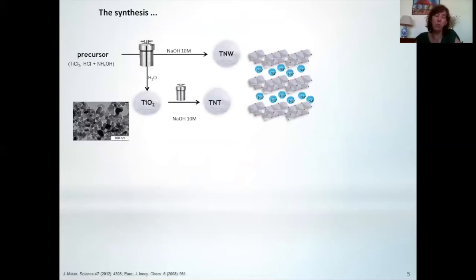problem by changing the source of the titanium. We are now using a different brand of the same compound, so we have no iron or manganese in the solid. So we prepare an amorphous precursor. After hydrothermal treatment, we are able to prepare titanate nanowires. If we put the same precursor in water, we will be able to prepare TiO2.